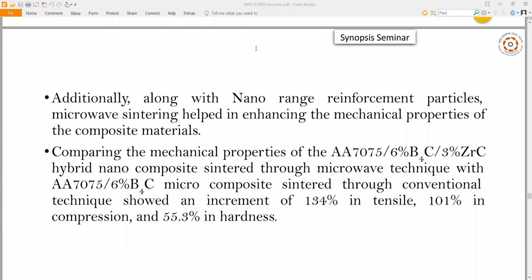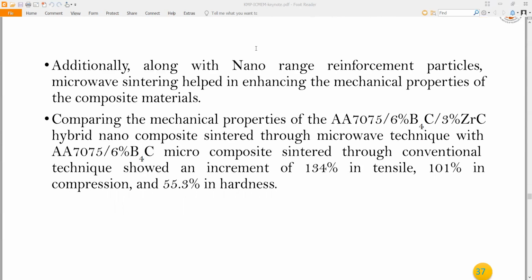Then additionally, along with nano-range reinforcement particles, microwave sintering helps in enhancing the mechanical properties of the composite materials. Comparing the mechanical properties of the AA7075, 6% B4C, 3% ZrC hybrid nanocomposite sintered through microwave technique with AA7075, 6% B4C microcomposite sintered through conventional technique showed an increment of 134% in tensile, 101% in compression, and 55.3% in hardness.